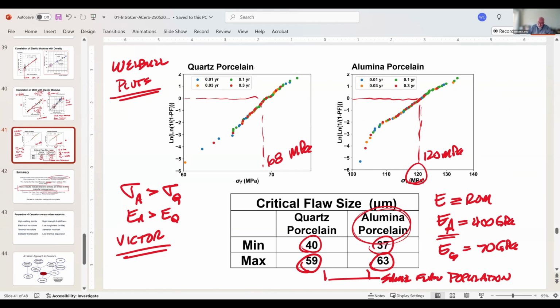What you see is that the quartz porcelain has a single slope. The alumina porcelain is slightly different, because the slopes are slightly different, because this one has a second flaw population. This is a manufacturing defect that is introduced in some portion of the process. This one doesn't have it. The quartz porcelains all have a single slope, so there's one flaw population that's incorporated in all. This has what's called an extrinsic flaw population, which we may get time to talk about tomorrow or Thursday, saying that this is where there's a potential for process control improvement.